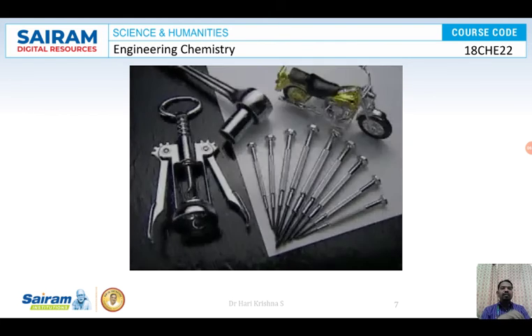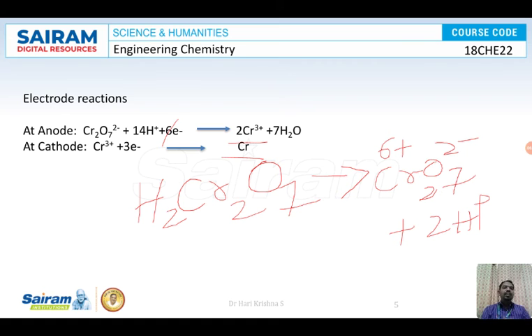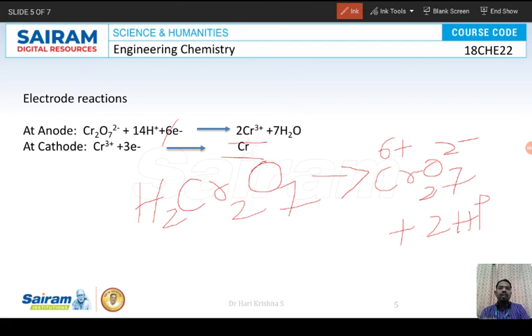Before going on, you can ask why chromium plating is done only using the electrolyte method, and why it is not done using the anode consumption method. As discussed earlier, the chromium anode strongly passivates in acid media. That is one reason. The other reason is that the anodic efficiency is 100%, that is, every minute 100 Cr plus 3 will be liberated, but at the same time only 10 to 20 Cr plus 3 will be converted to Cr.